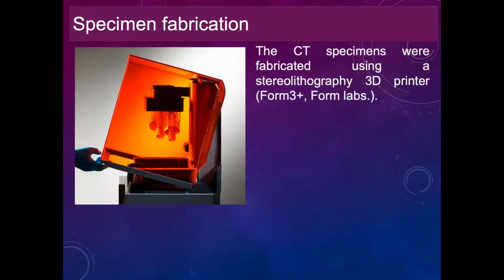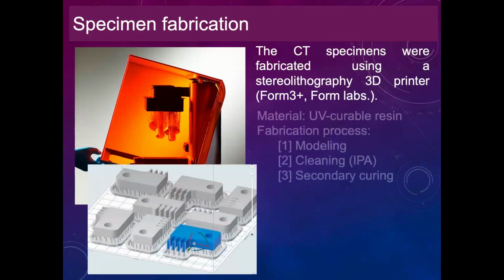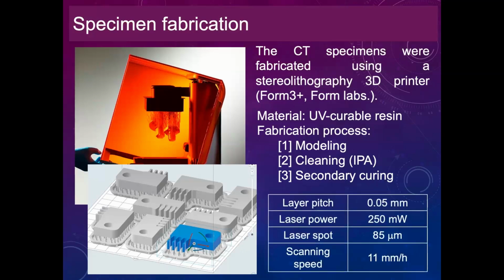The CT specimens were fabricated using a stereolithography 3D printer. In this study, we used the Form 3 Plus from Formlabs, as shown here, and the material selected was UV-curable resin. The fabrication process has several steps, and this table shows the process parameters for the 3D printer in this study.